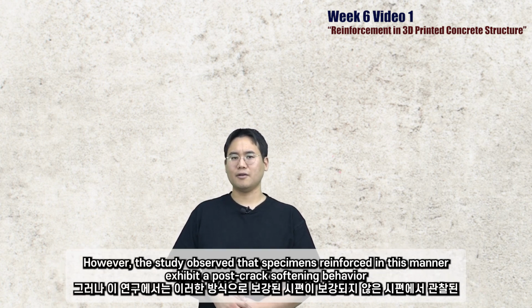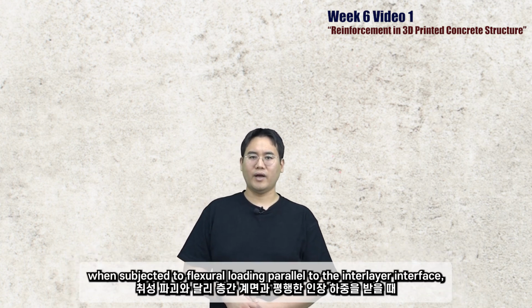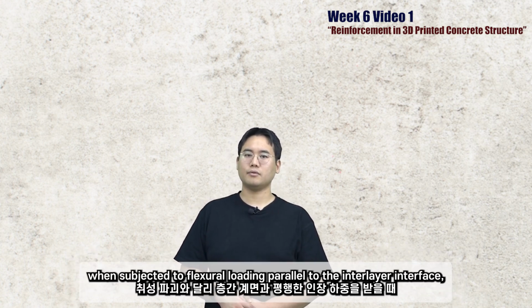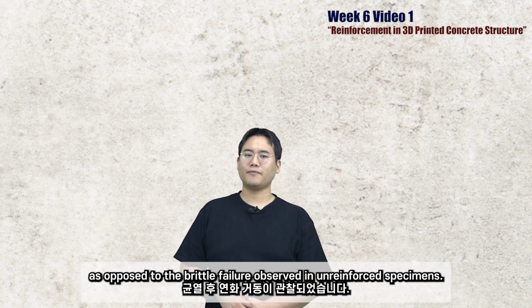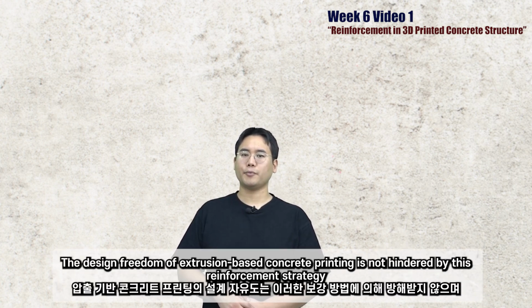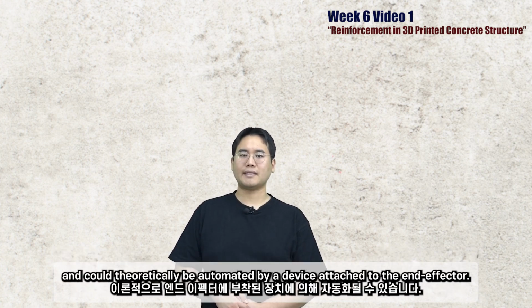However, this study observed that specimens reinforced in this manner exhibit a post-crack softening behavior when subject to flexural loading parallel to the interlayer interfaces, as opposed to the brittle failure observed in unreinforced specimens. The design freedom of extrusion-based concrete printing is not hindered by this strategy, and could theoretically be automated by a device attached to the end effector.